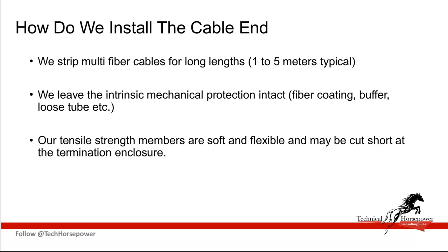In other cases, we are taking the fibers and breaking them out into individual fanout tubes to put single fiber connectors on them, or breaking out a bundle of fibers or a ribbon to put into a 12, 24 fiber connector, such as an MPO, and so forth. So we have to strip longer lengths for access. We can't afford to damage that core in the process. So we have to leave the intrinsic mechanical protection intact.